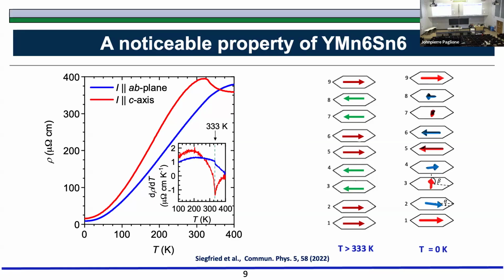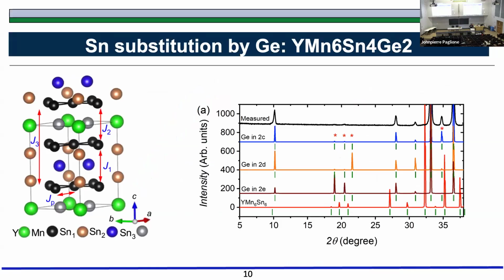But now, as I told you, our goal was to tune these various different properties. And how do you tune it? We took the same material, and we wanted to keep it simple, not very complicated. I told you that there were 3 inequivalent tins, right? And the advantage of that is that you can replace one of the tins and put back another element. The nice thing is, let's keep the electron count the same. So let's look at the periodic table, and tin is here. If I put germanium, the germanium has the same electron count. It necessarily will not change the electronic structure. But what it does is that it has a smaller size. So it can shrink the crystal structure, right? When it shrinks the crystal structure, what changes can it bring in the magnetic structure, or even in the electronic structure, because of the magnetism?